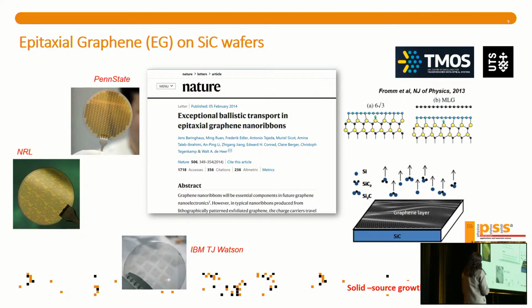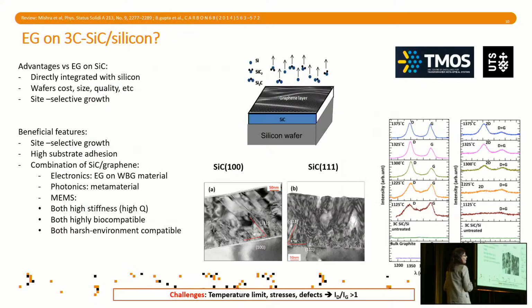A lot of work has been done already in the epitaxial growth of graphene on silicon carbide wafers, so hexagonal silicon carbide. These were early examples from quite a lot of leading groups around the world, and quite a lot is known about how this growth goes. It goes through a buffer layer and then forms a quasi-freestanding layer of graphene on top. It can happen indeed at a wafer scale, but you need to use silicon carbide wafers. And remember, we really wanted to have this on silicon. So what impedes this from being transferred to silicon? Unfortunately, a lot of things.